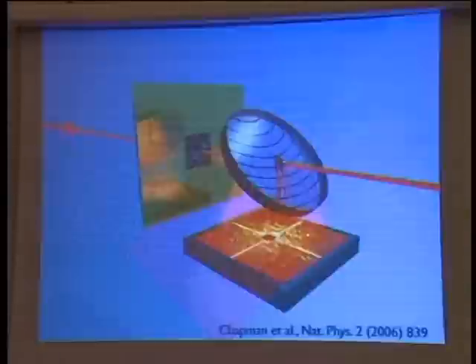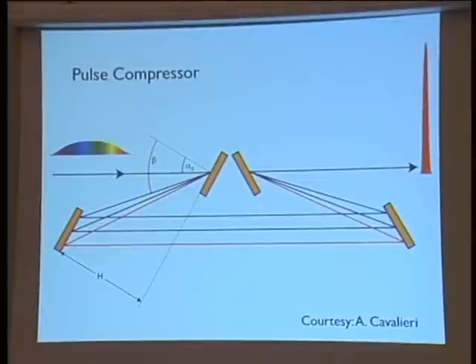What's also very important to show is that this particular experiment, and many more after it, was enabled by multilayer-based optics. In this case, the multilayer optic was not used to focus the X-rays, but was used as part of the detector. We are here reflecting the scattered light from the sample into the detector, and very nicely filtering the signal as well. That was very important for this experiment.